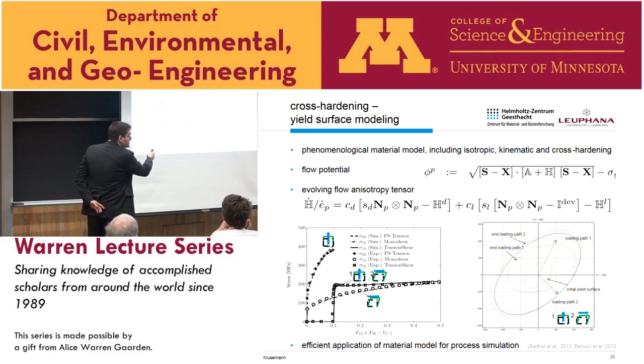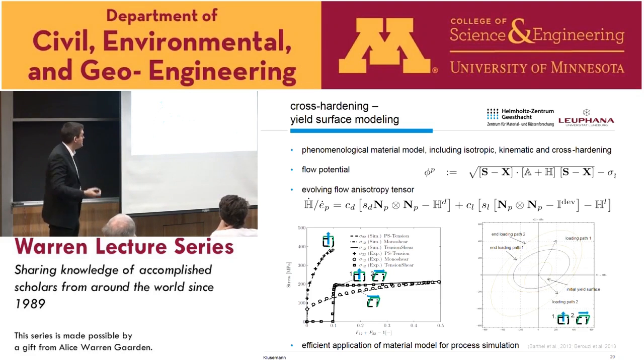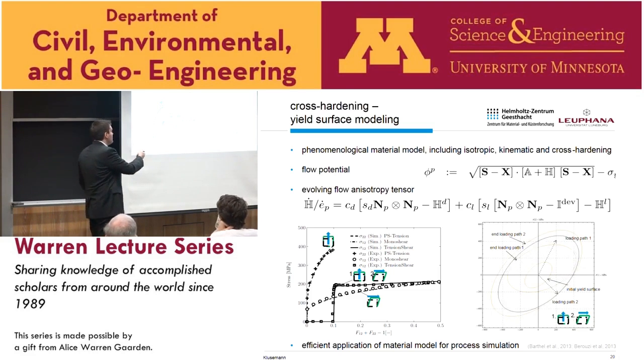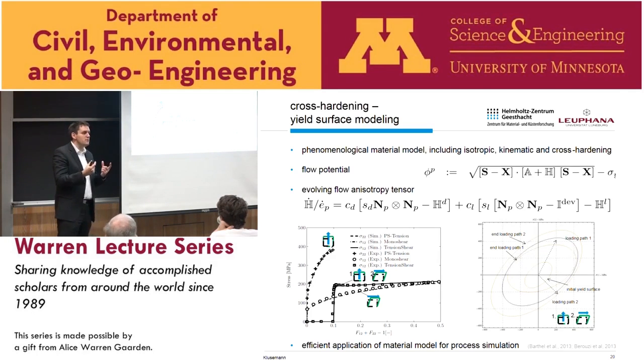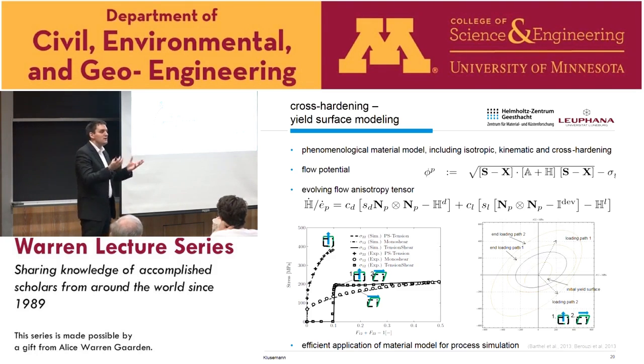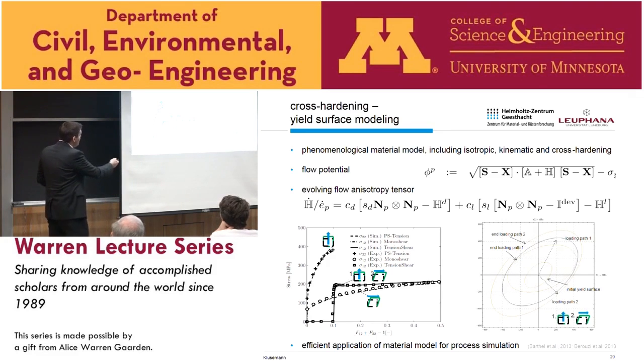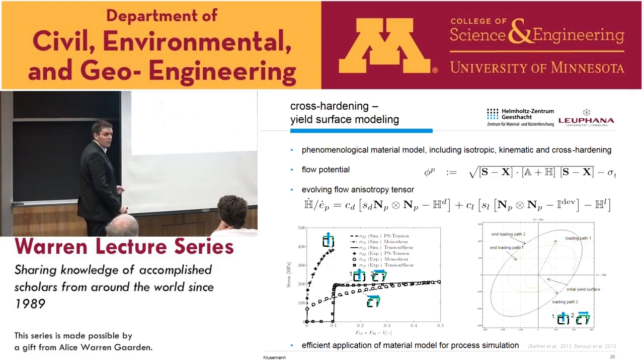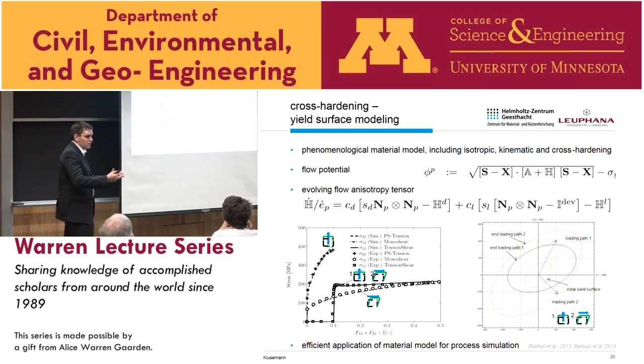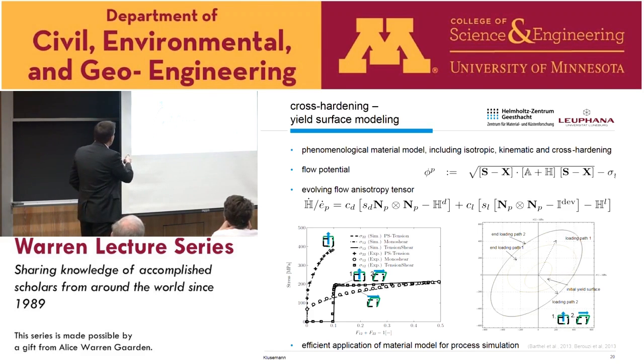Well, we formulated this in terms of this flow potential. We have here, first of all, S, which is simply our macroscopic stress, so the Cauchy stress. X is our kinematic stress, where we have an evolution equation for kinematic hardening, for which we used the Frederick-Armstrong form. Then we have this fourth-order tensor A, which is our initial material anisotropy. For example, it could be Mises, if it's isotropic in the beginning, or here we used, for example, Hill. And then we have this tensor H, which is our evolving flow anisotropy tensor. I'm coming to that in a second. And then additionally, we have here our isotropic hardening contribution. So very classically, as always done.